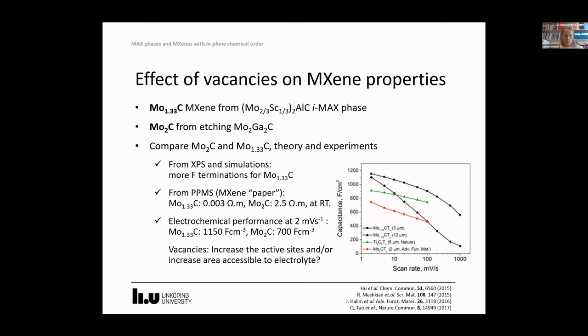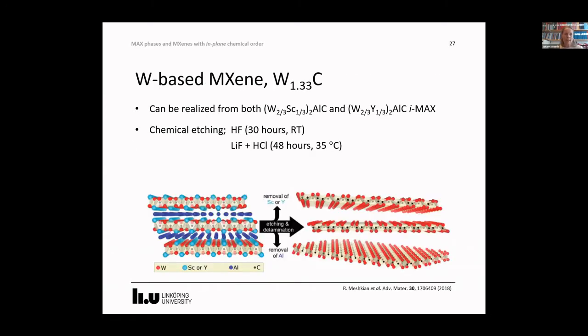Yes, so we have also investigated vacancy MXene based on tungsten. These results are part of another theoretical screening study where we evaluated the phase stability for tungsten-containing i-MAX phases based on different A elements. We found these two i-MAX phases, and it turned out that both of them could be etched in either HF or lithium fluoride plus HCl, both realizing vacancy MXenes.